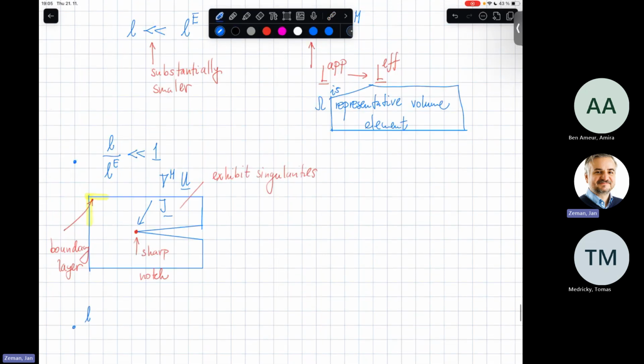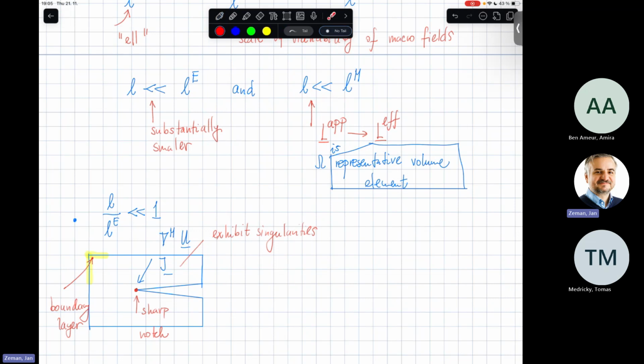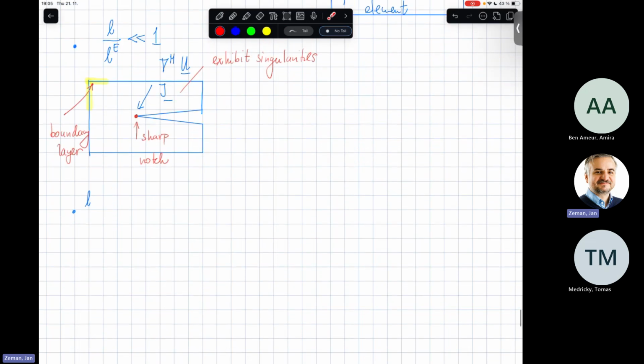So if I would now be interested in the case that I take the second ratio and take this RVE, which is the size of my homogenization window, so if this is not valid, it is substantially larger than 1, then the example which is used in that Huet's paper is that you are making some structural tests, and again, this will be my naive drawing, and here you have some aggregates which are of this size.